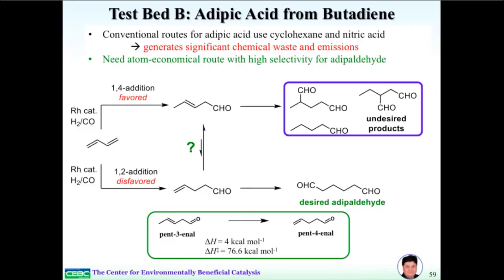The test bed B here involves starting off with butadiene and trying to convert it essentially to a dialdehyde, which can then be easily converted to adipic acid, the precursor for nylon. The conventional process for this involves a starting material of cyclohexane and uses nitric acid, and it generates NO2 as a waste product, but it also still generates a lot of residual nitric acid in the system. And so a cleaner alternative would be to actually look at a rhodium catalyzed